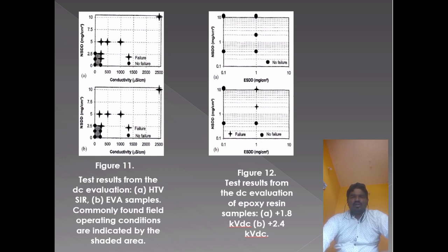in a much poorer electrical performance of the polymers, which is evident from the results presented in figures 11A and 11B. Sample failures occurred not only at high pollution levels but also under pollution conditions likely to be found in a large number of locations worldwide. This is of major practical importance, since failure of these polymers would be anticipated at electrical stresses in a range close to that commonly used for non-ceramic outdoor insulating devices selected for DC applications.